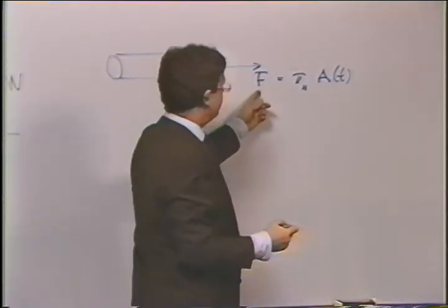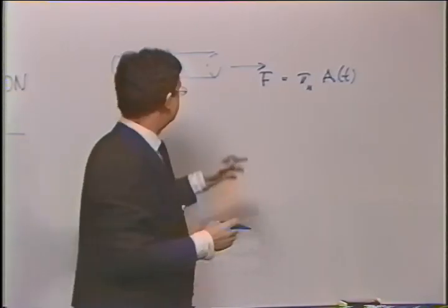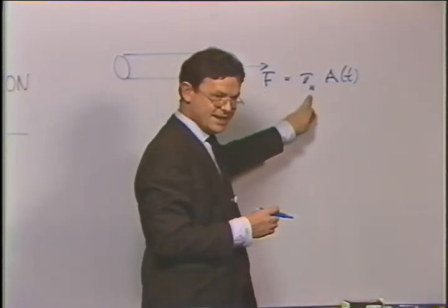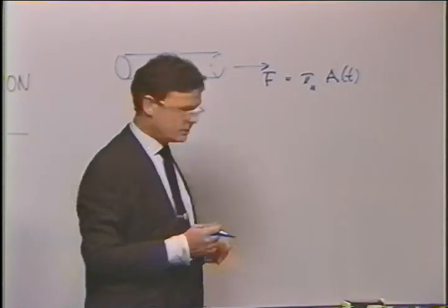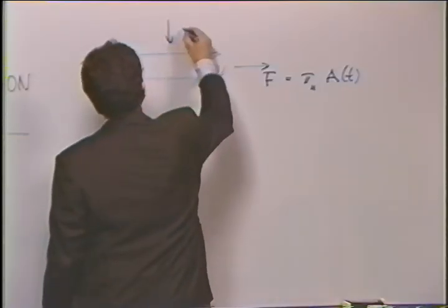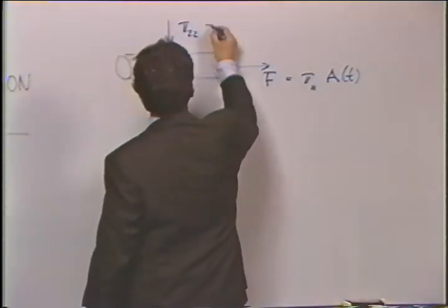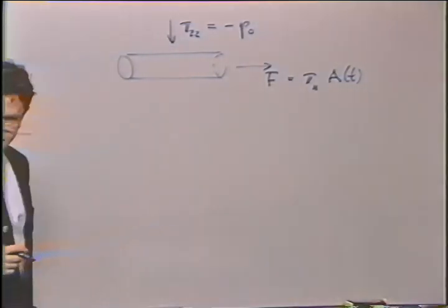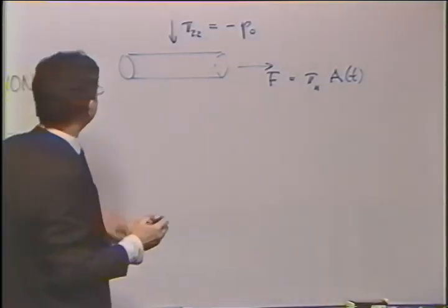Now, in a real experiment, and let's postpone the discussion of how to do that, your transducer would see the total force, and if this stress response is constant, the force decreases as the fiber gets thinner and thinner, and that will be a limitation. It's a very hard experiment to do. Okay, so this is the force, and sideways, there will be a normal stress on that surface, and this normal stress is equal to minus the ambient pressure on this side. So it's basically 0 under most conditions if we have a large stress acting on the system.